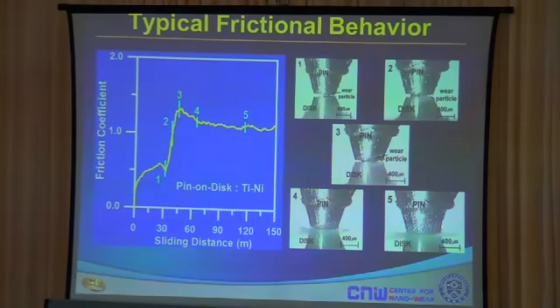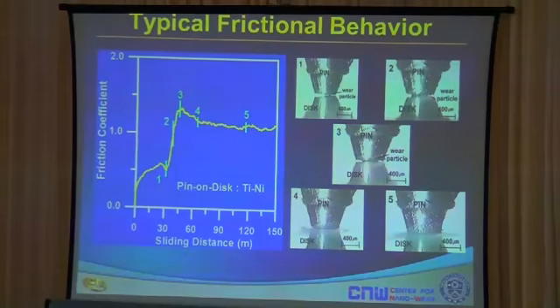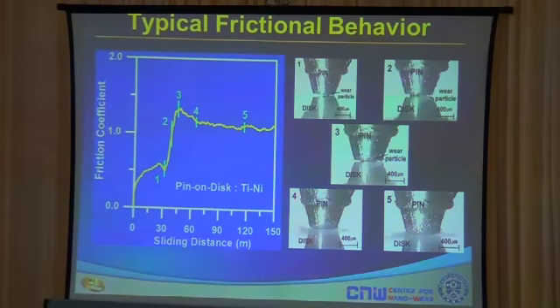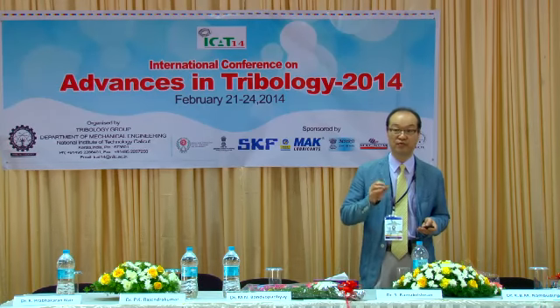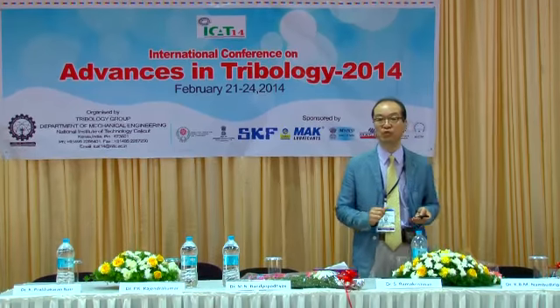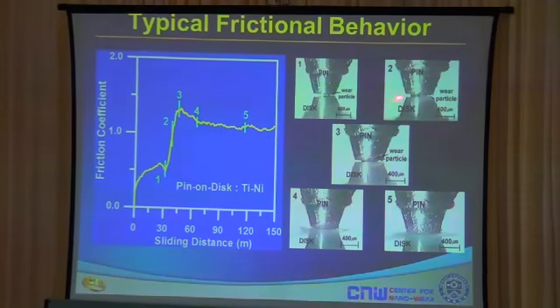The point of interest is, why does this friction coefficient increase? Well, if we observe the sliding interface with a microscope, with a pin, and this is a flat surface here, the thing that you see here is a reflection. So you may ignore this cone-shaped thing at the bottom. It's just a reflection of the top surface. Bottom surface is flat. At the point at which the friction coefficient starts to increase, we see the creation of a significant wear particle. And this particle serves to damage the surface by way of abrasion and micro-cutting. Obviously, the friction goes up. And once enough number of particles are created at the interface, you reach a steady state as the particles are ejected from the interface and also created at the interface.